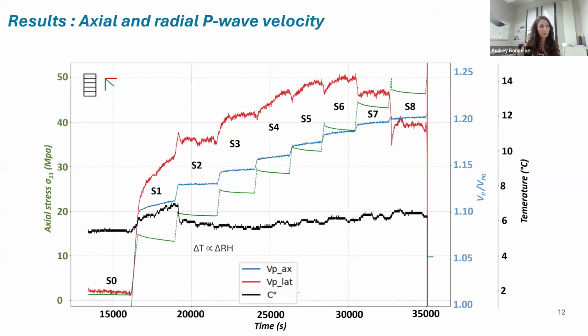During our experiments, as I mentioned earlier, we've also been measuring the evolution of P-wave velocity, which is usually used as a proxy to understand compaction and dilation. Compaction means that we are compacting all of the pre-existing porosity, which can be divided into classical porosity and crack porosity. And dilation is usually associated with the generation of damage inside of the sample.